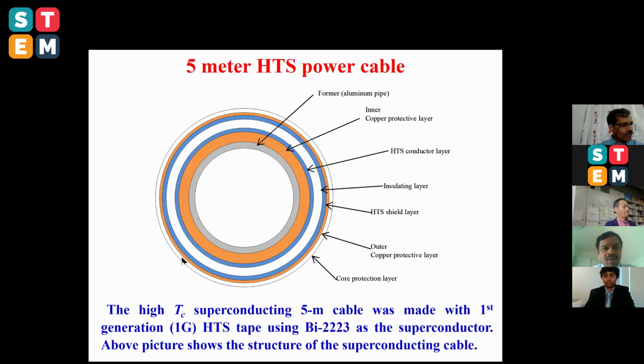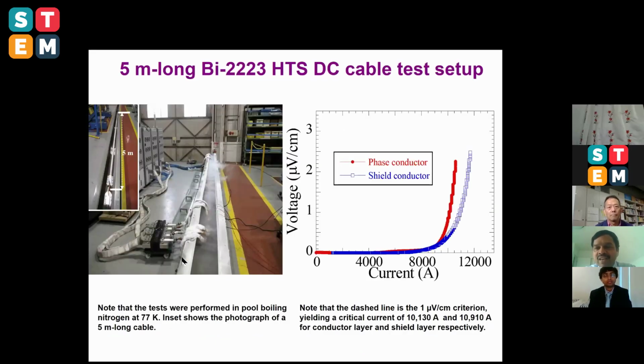Then we ordered a 5-meter cable. In this case, we first used the copper former, but this copper former is very heavy. Then in the second stage we used aluminum. Then they also made a hole to pass the liquid nitrogen, and also to control the fault currents. Along with the superconducting layer, we used the copper protection layer, both positive and negative. Then we tested the IV curve of the bismuth 223 5-meter cable dipped in liquid nitrogen temperature. You can see here the 5-meter cable dipped into the LN2 bath. Then we found critical currents of about 10.13 kA and 10.91 kA. This is very close to what we expected.